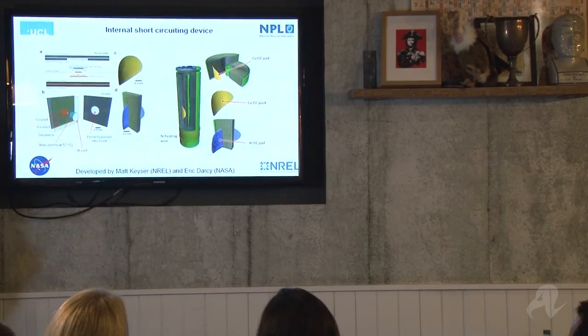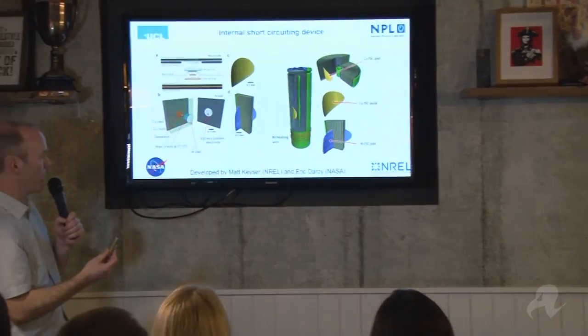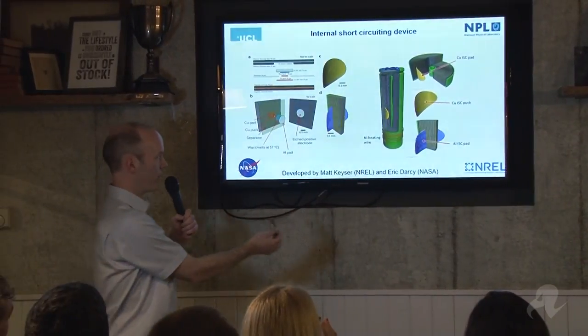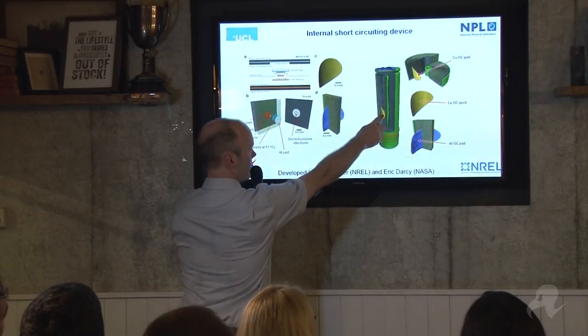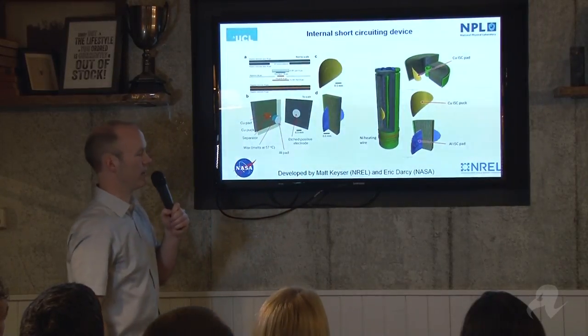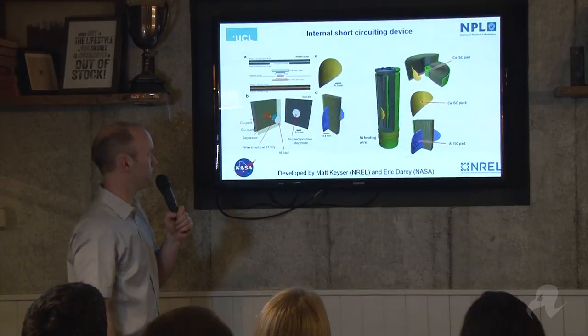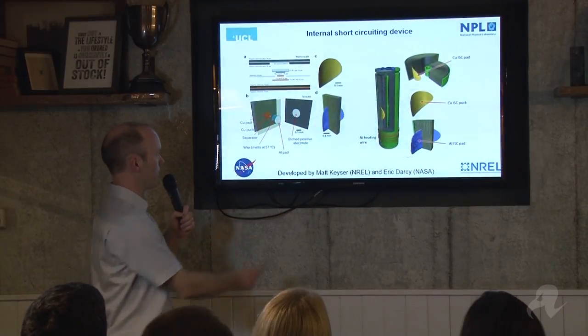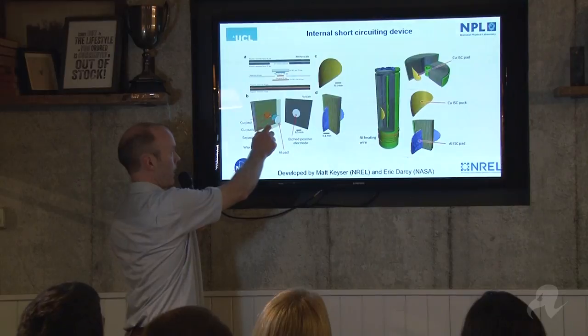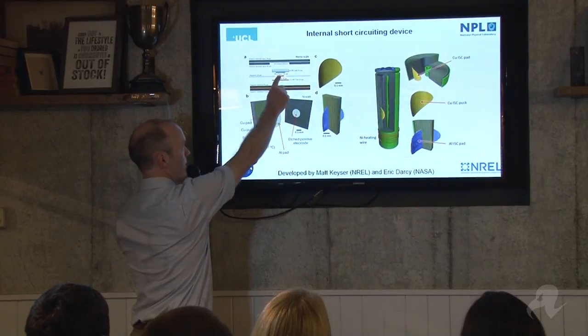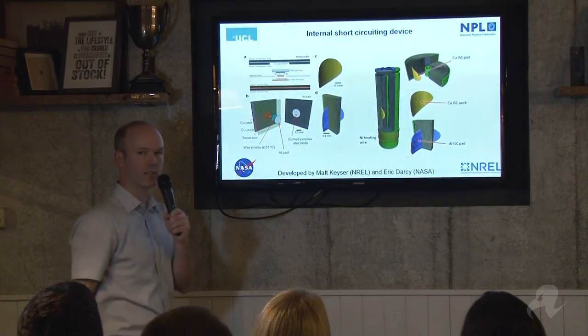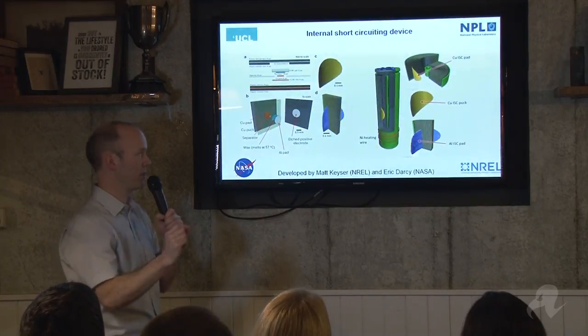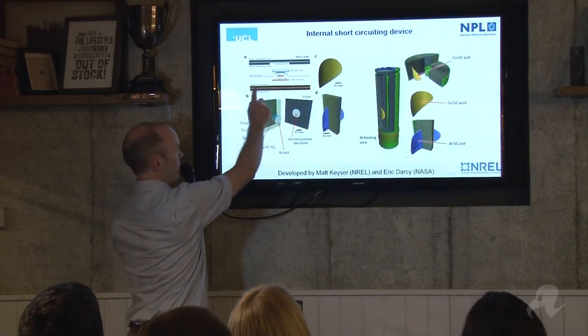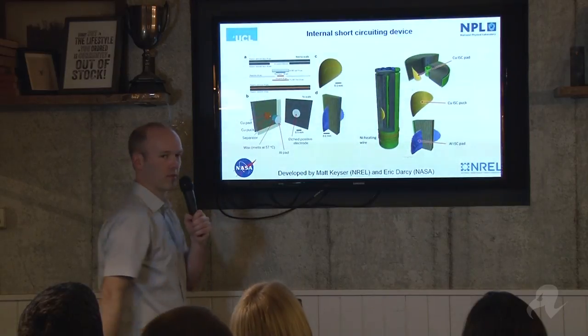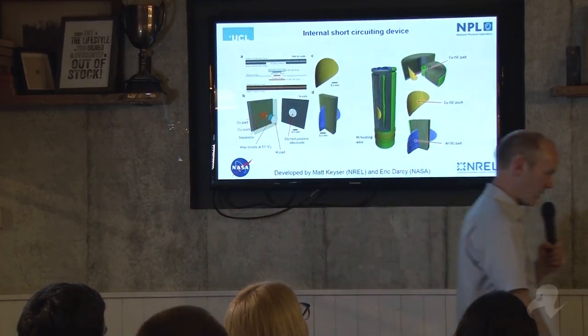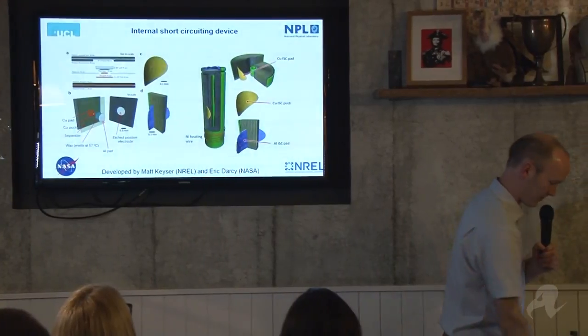So we had a special cell made. We had two, in fact, with this device located somewhere in between the sidewall and the central mandrel. And then, as I said, we heated up the battery. This layer of wax melted. These things made contact. And then you got a local short circuit between the copper negative electrode and the aluminium positive electrode. And I'll show you what happened in the next slide.